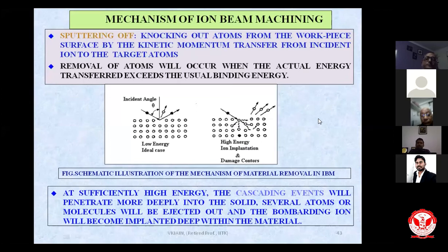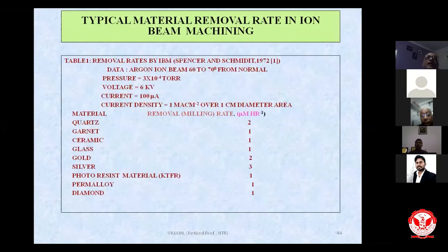Now, I have told you that this particular process is not good for micromachining, rather it is good for nanomachining. As you can see in this table, prepared by Dr. Arvind a couple of decades back for his PhD thesis, the material is here, and the material removal rate is here, in micrometer per hour. Quartz, you can remove 2 micrometer per hour, ceramic 1 micrometer per hour, gold 2 micrometer per hour, silver 3 micrometer per hour. So it's a very low material removal rate.